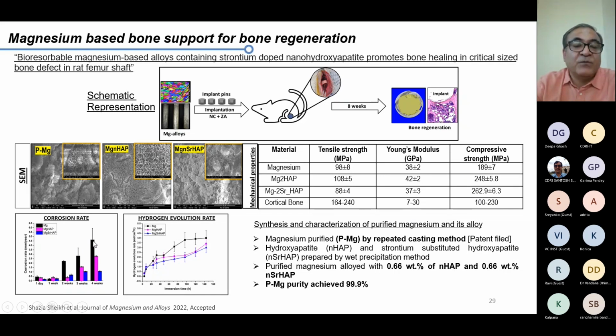Obviously, the black one, what is showing the bar here, is just simply the magnesium, which has corrosion. But when you have magnesium HAP or magnesium strontium HAP, you have decreased this corrosion rate significantly. Hydrogen evolution rate has also decreased significantly.